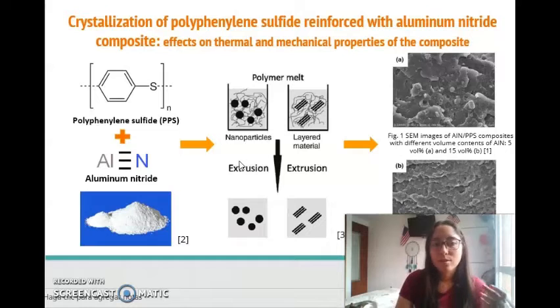So for the filler content of 5%, the aluminum nitride particles were observed to disperse randomly at the fracture zone, and the interfaces between the aluminum nitride fillers and the PPS were presented clearly. However, it was difficult to distinguish the interfaces between the filler and the matrix when the composition was 15%. The results also show that the thermal conductivity of the aluminum nitride and PPS composites increased with the addition of aluminum nitride in various amounts, by forming a conductive network with the composites due to the filler. So now we are going to talk about the tests that were carried out to analyze this new composite.